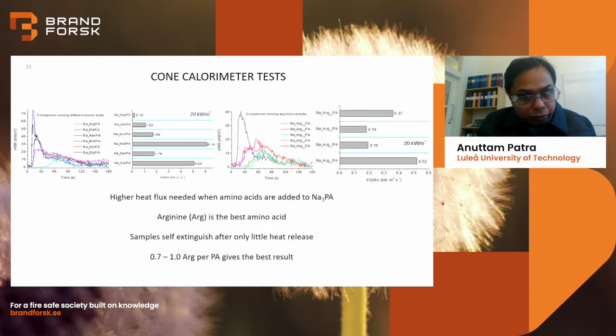That is really good, but there is one inherent problem. These are sodium salts. And you know, monovalent ions like sodium, potassium, ammonium, they are always water soluble. And these ones are no exception. So although this flame retardant is good, we can use this where there is no water exposure, like inside the building material. But if you put it outside a building, if there is a rain, it will be washed away. If you use on a cloth and do the washing, you will lose all flame retardants. So we need insoluble flame retardants.